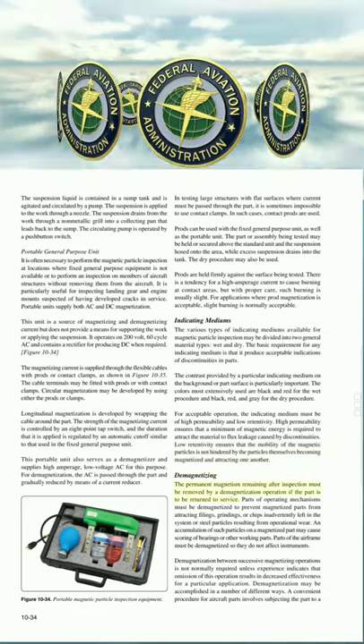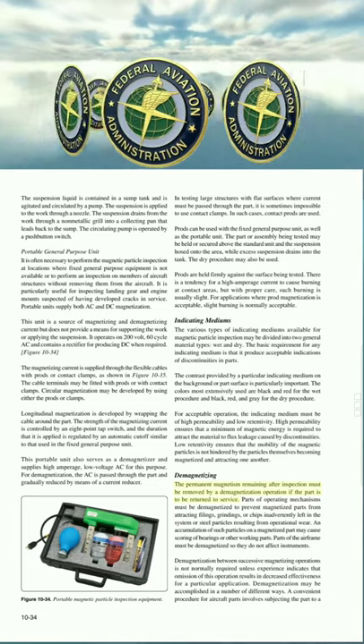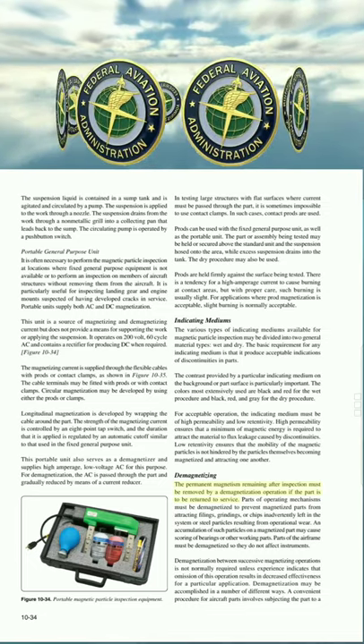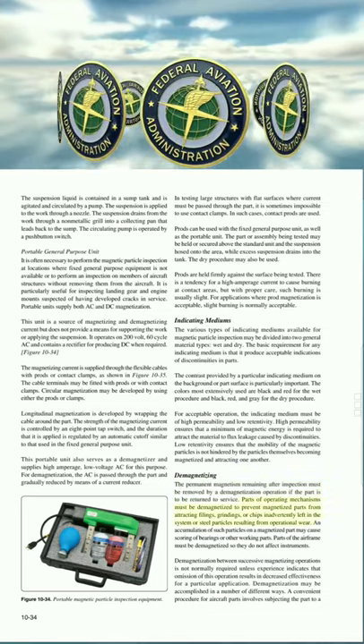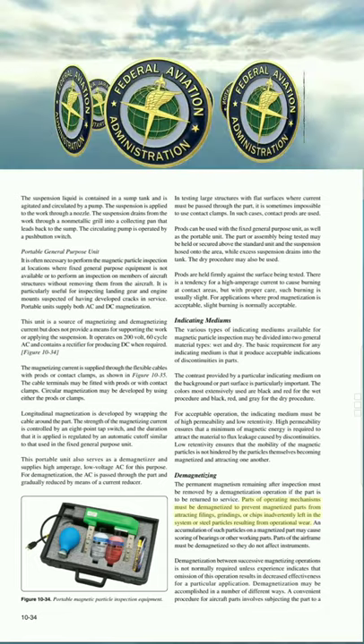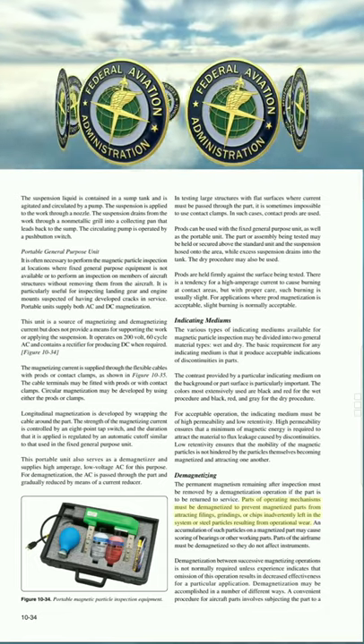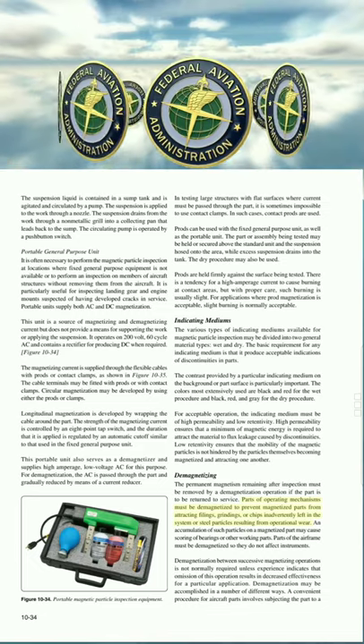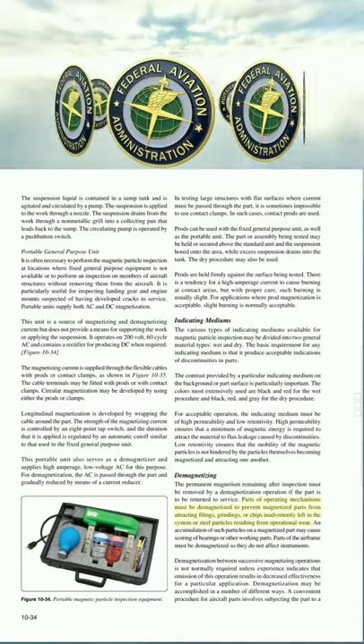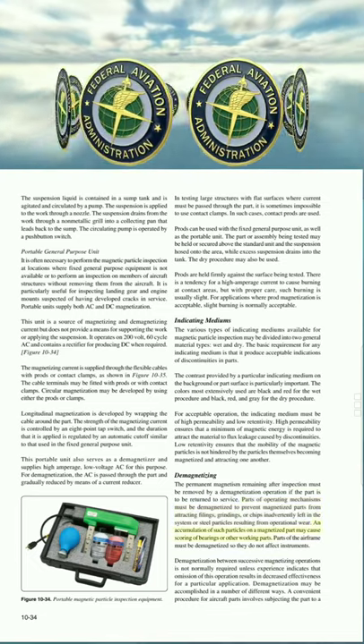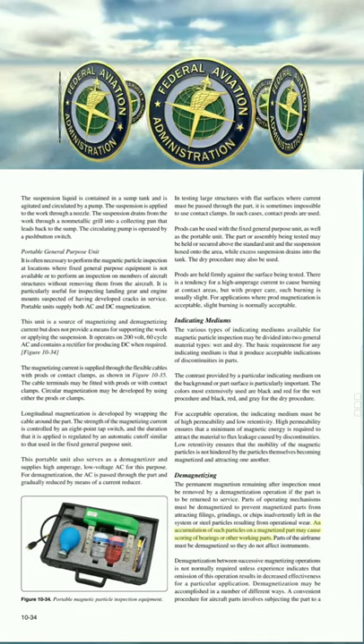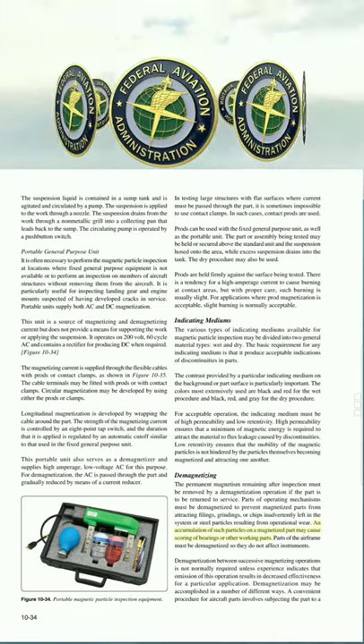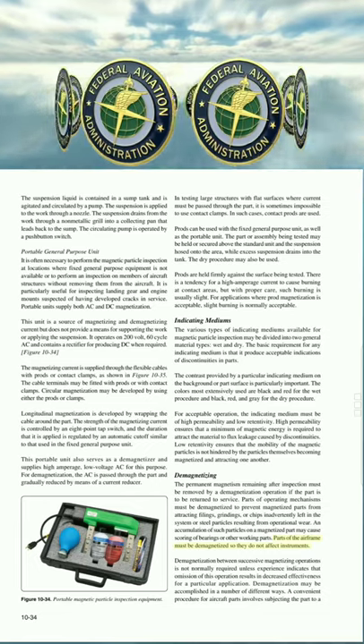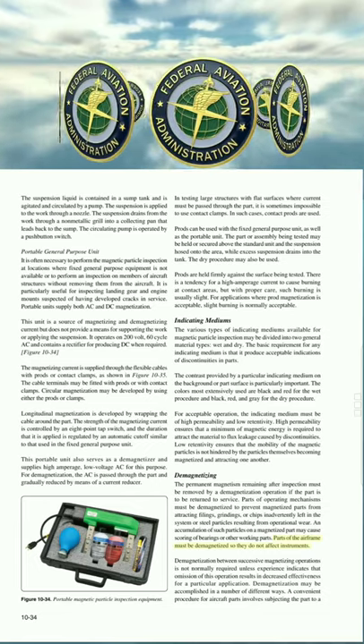The permanent magnetism remaining after inspection must be removed by a demagnetization operation, if the part is to be returned to service. Parts of operating mechanisms must be demagnetized to prevent magnetized parts from attracting filings, grindings, or chips inadvertently left in the system or steel particles resulting from operational wear. An accumulation of such particles on a magnetized part may cause scoring of bearings or other working parts. Parts of the airframe must be demagnetized so they do not affect instruments.